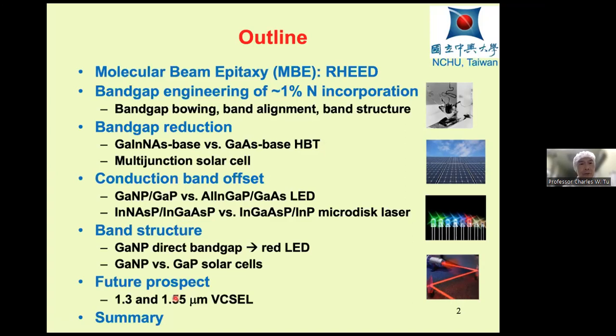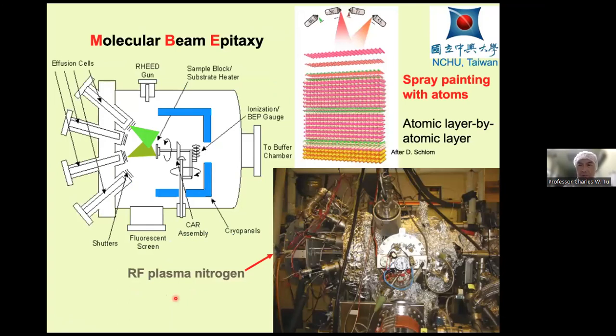So molecular beam epitaxy is a highly versatile thin film growth technique. It's growing layer by layer, and it's done in an ultra high vacuum condition. Atmosphere is 760 torr. Ultra high vacuum, we are talking about 10 to the minus 9 torr. Here we liken MBE to spray painting with atoms, meaning that in the growth chamber, we have effusion cells with materials like gallium, arsenic, aluminum, indium, and so on. We heat them up to high temperature so that we have atoms diffusing out. But to stop them from coming out, we put a shutter in front.